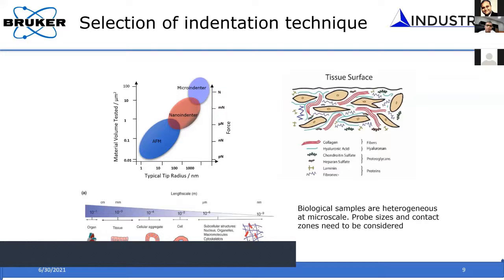But if you wanted to go beyond that, you need to use some AFM-based technology, because the forces that you require are much lower than nanonewton. Sometimes you have to go into the piconewton length scale, with displacements less than 0.1 nanometers, so picometers basically. So in that case, you can use AFM-based technology to develop biomechanics understanding of the material, right? So it all depends upon the length scale that you want to study, and you can have different types of instruments, a microindentation, a nanoindentation, or AFM, or different types of probes, a spherical probe, a bigger probe, or a flat probe. So you have this ability to change, and you can make these measurements locally where you are trying to understand. So that is the advantage of this kind of technique.